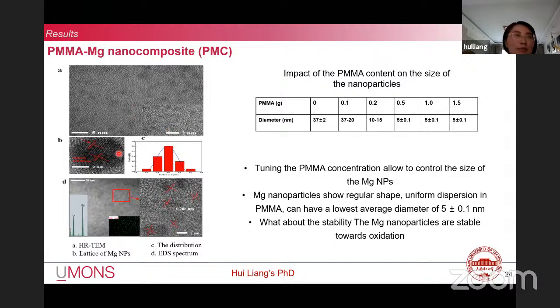Regarding the TEM images, Mg nanoparticles show regular shape. And we can also find the Mg nanoparticles were uniformly dispersed in PMMA. The Mg nanoparticles are stable towards oxygen. Refer to the diameter distribution figure of Mg nanoparticles: its average diameter is about 5 nanometers.